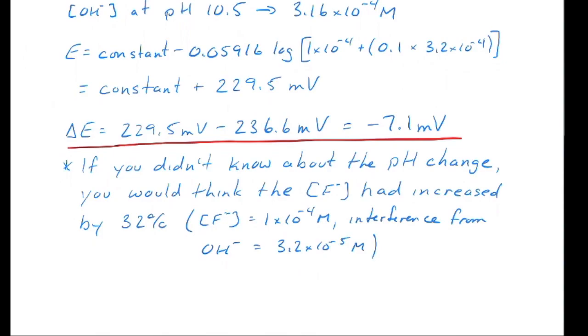that the concentration of fluoride had increased by 32%. And we get that from basically this up here. Right? So we have our initial concentration of fluoride of 1 times 10 to the minus 4, but we're adding 0.32 times 10 to the minus 4. So we're giving it a 32% boost in concentration.